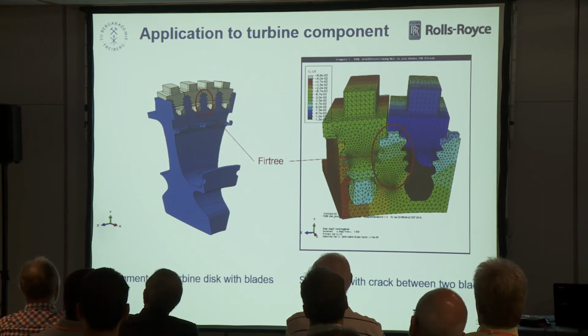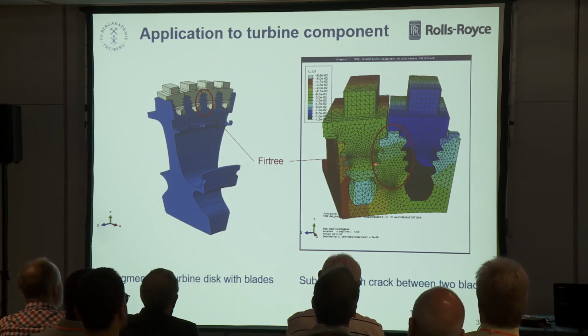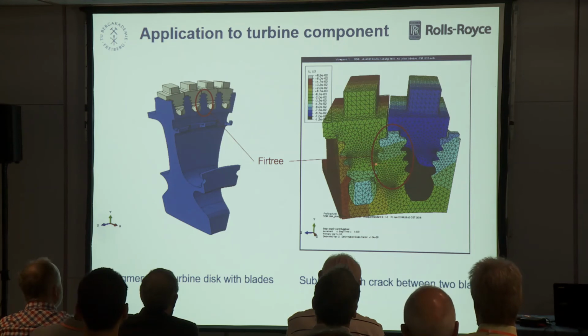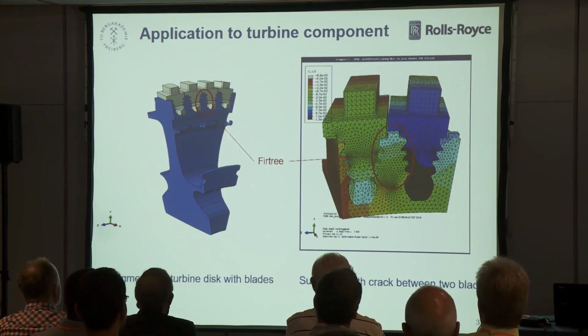So we assume a crack, a corner crack here at the edge of this fir tree. Now we made again a submodel. Here two blades, and this is a disc, and here this fir tree. Here you see the deformations. This is a submodel, and now we start our crack work.